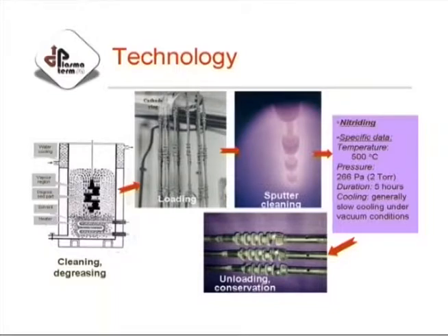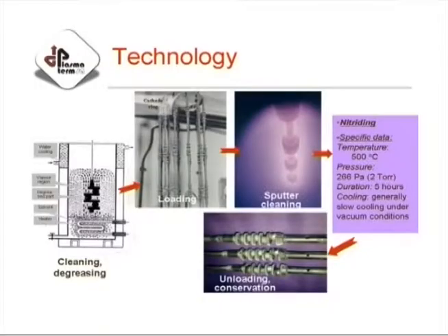It's much more important than for carburizing, because here the temperature being low, the surface activation is extremely important. And we were dealing for many years to study the influence of surface activation on nitriding, so what happens when some passivated layers appear, and passivation will not necessarily always disappear just due to the cathode sputtering. Then the loading, which has to follow a specific structure to assemble the parts so that we can have a glow discharge as uniform as possible. The next one, when we start the process, first, it will be a sputter cleaning of the parts, which will remove practically all the oxide traces and anything from the surface.